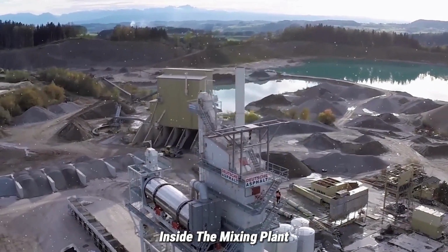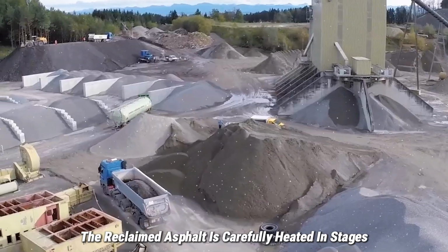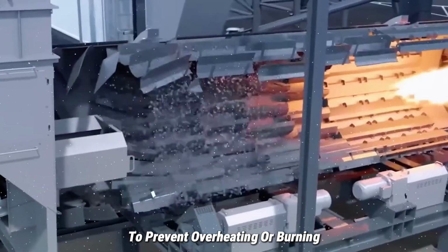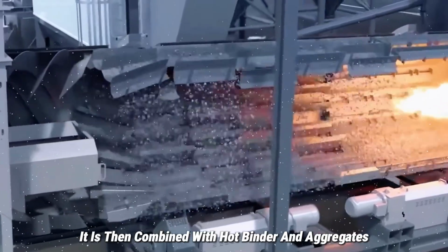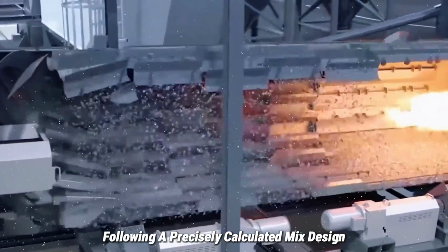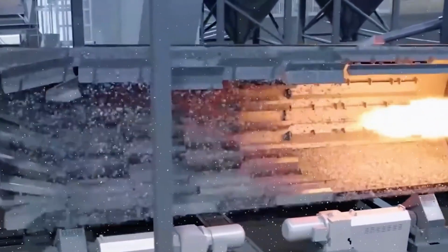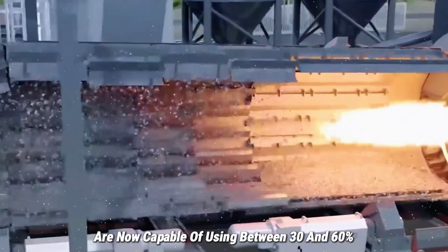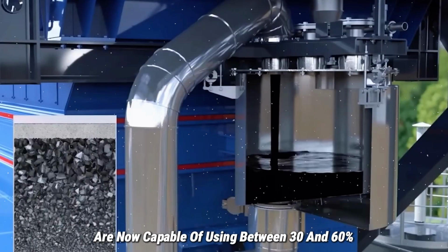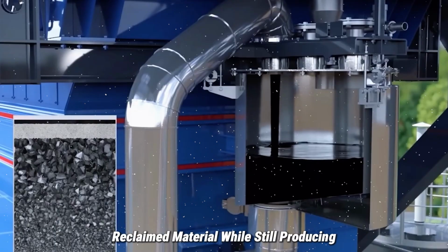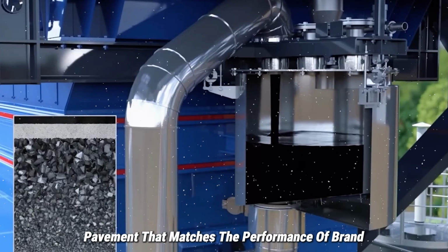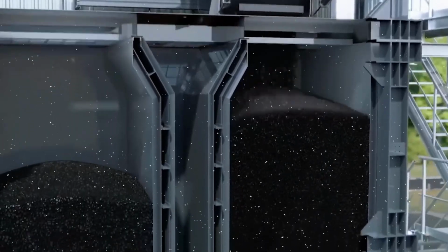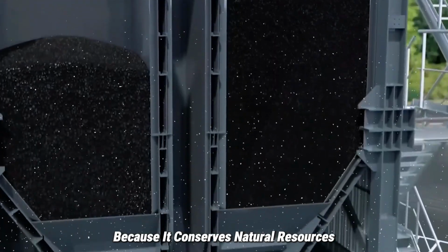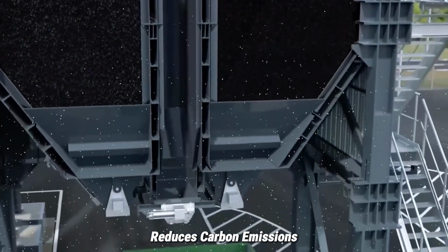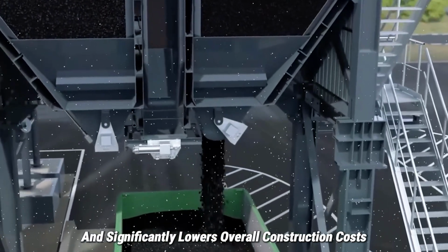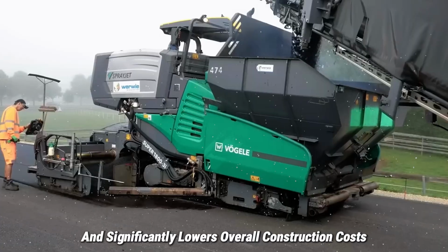Inside the mixing plant, the reclaimed asphalt is carefully heated in stages to prevent overheating or burning. It is then combined with hot binder and aggregates following a precisely calculated mix design. Many modern asphalt plants are now capable of using between 30 and 60% reclaimed material while still producing pavement that matches the performance of brand new asphalt. This process is especially important because it conserves natural resources, reduces carbon emissions, and significantly lowers overall construction costs.